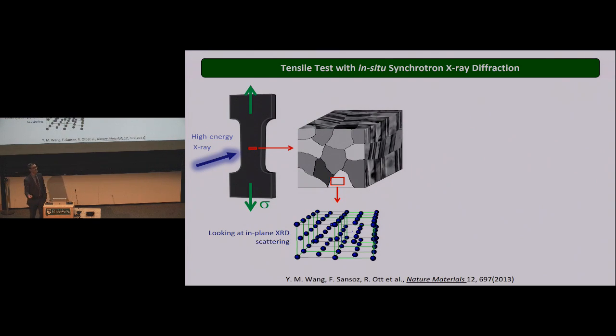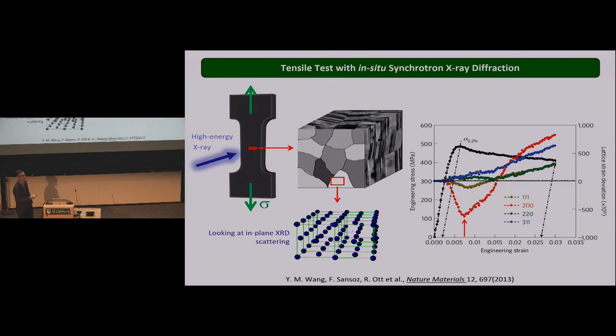The experimentalists did the same, and now they use in situ nanomechanics. The first test is a synchrotron X-ray diffraction experiment where we make a film. This is a close-up view of the film. We stretch the film and, at the same time, expose it to high-energy X-rays. That gives us information about the way the crystal planes deform elastically inside the crystal in real time. All right. And what we found at the time was very abnormal.